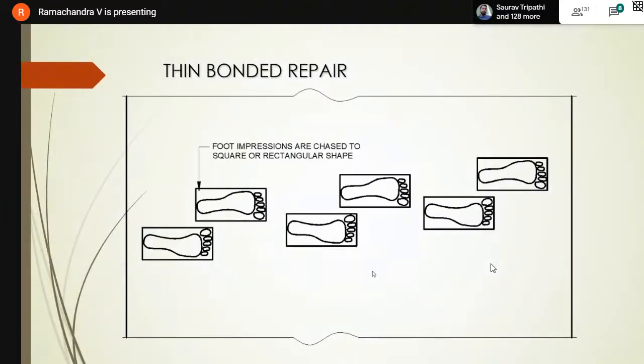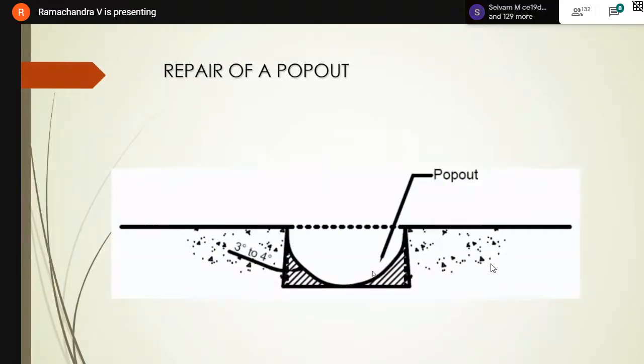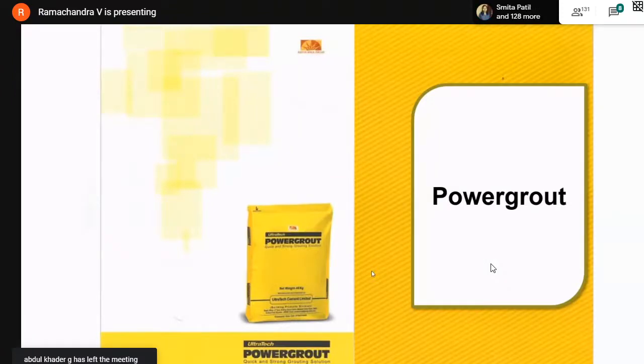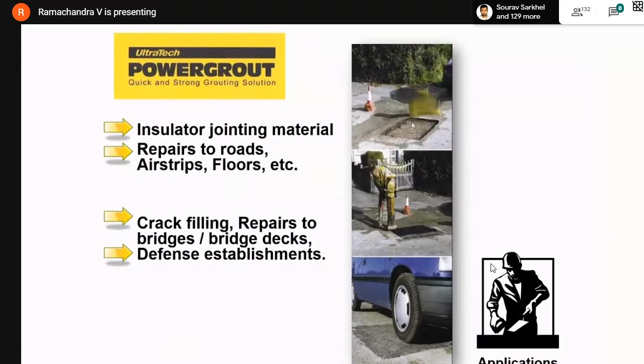Even these foot marks or pop-outs due to foot marks should also be made rectangular and then repaired. Now this pop-out, make it into a rectangle as shown in the figure. You have a lot of materials. Even UltraTech has a material called power grout. If you put this power grout into this, as you can see here, you cut it as a rectangle and then put it, and this has the property of getting 40 MPa of strength, not after 28 days, but 40 MPa of strength in 24 hours. That is 1 day strength. You get so much that it can be opened to traffic.